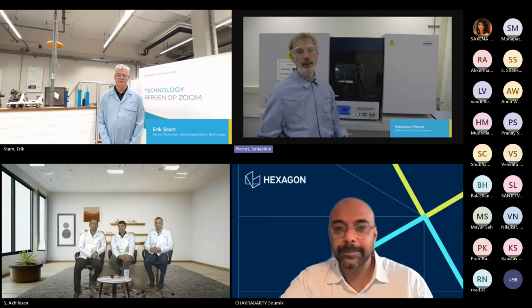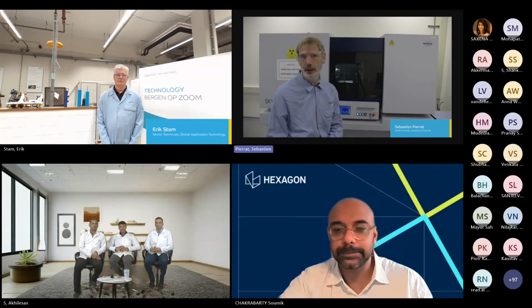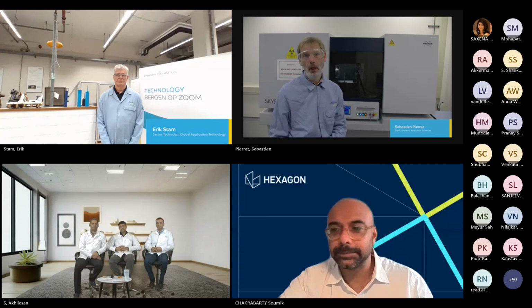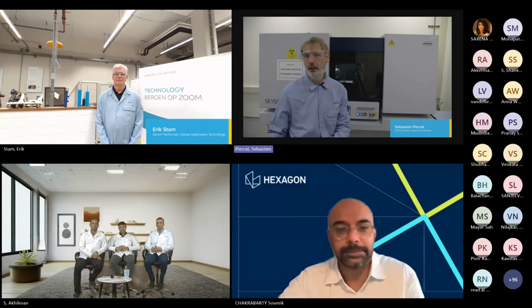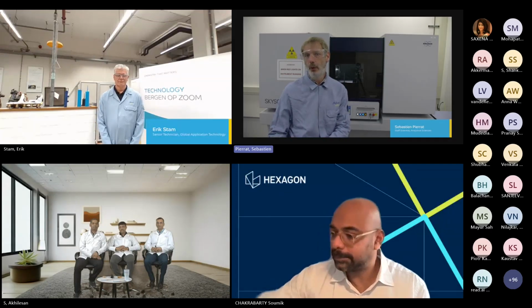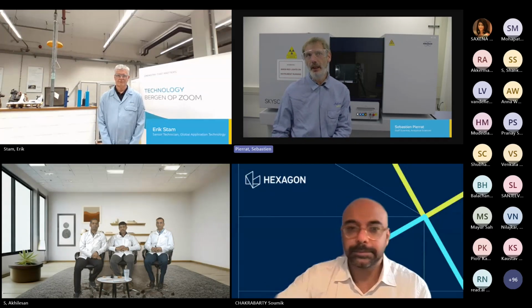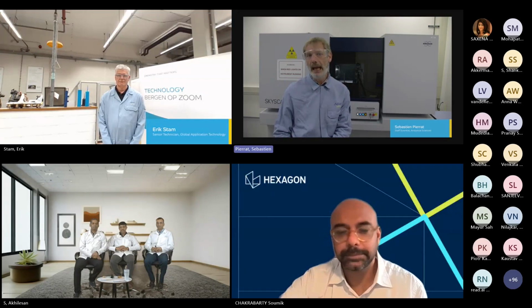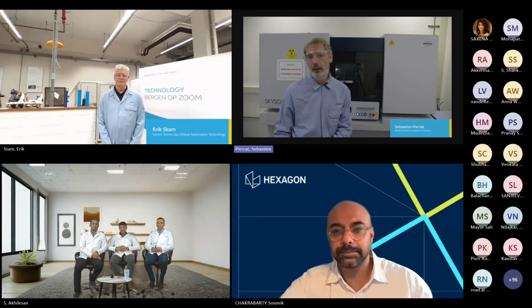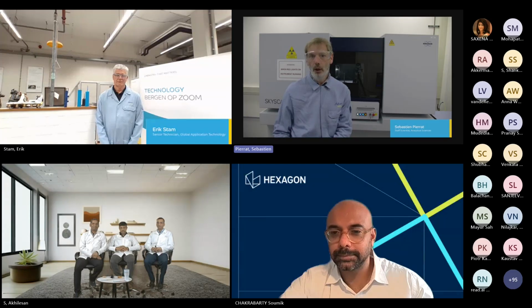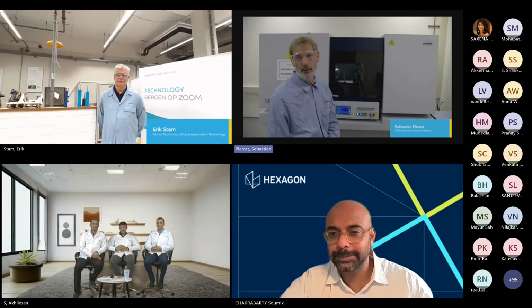All right. So there's a very strong correlation between the resolution that we want to achieve and the size of the sample. The higher the resolution is, the smaller the field of view is, and the smaller the sample should be. Typically, if I use a resolution of 40 micrometer, I can scan a sample of 10 centimeter. If I use a resolution of about 3 micrometer, I can scan a sample which is about 12 millimeter. And if I want to achieve pixel sizes below 500 nanometers, then we are talking about samples which are in the millimeter range.